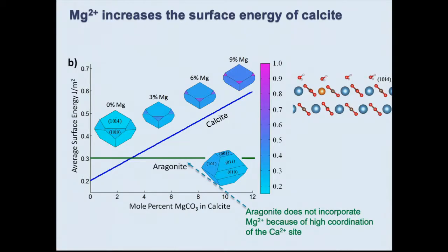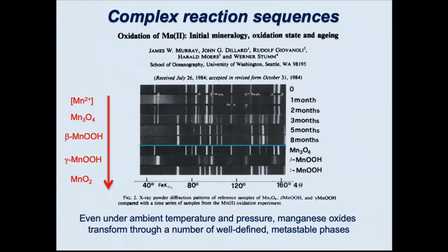So what you see happening now is if you go into high magnesium environments, calcite is still the more stable phase, but it actually has the higher nucleation energy because it has a higher surface energy. Again, so this is an idea of thinking of these more enlarged spaces. In some cases, you can get truly complex reaction sequences, and what we're learning is this is actually more common than we thought. This is an old experiment. My students call this old because it's from 1984. I shrug when they say this is old.